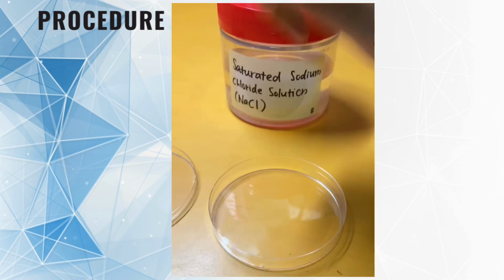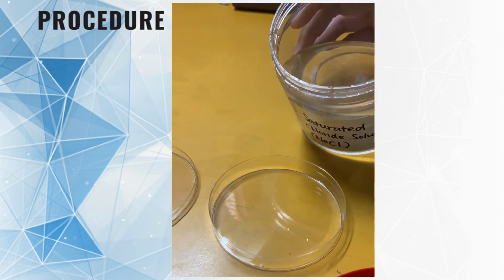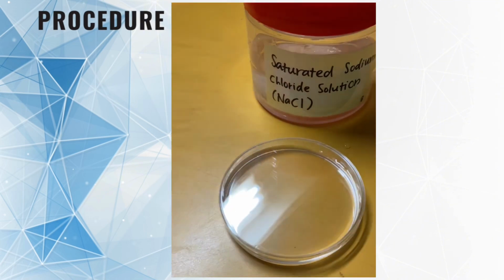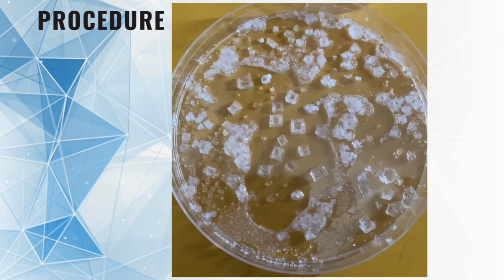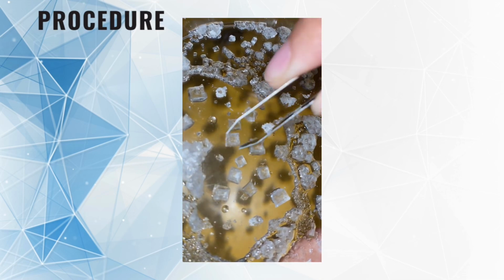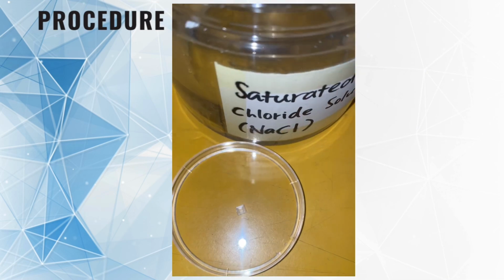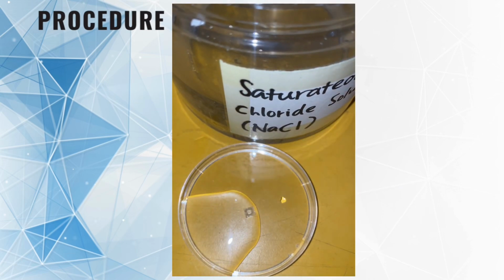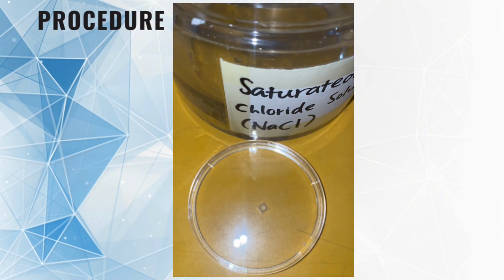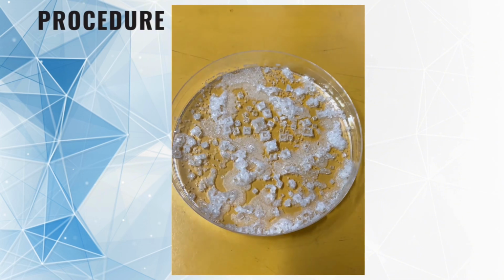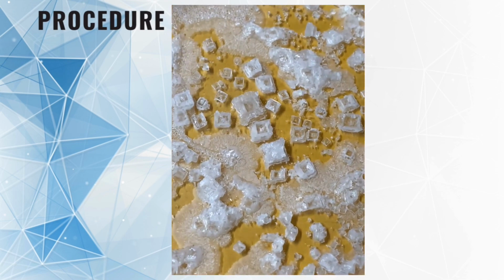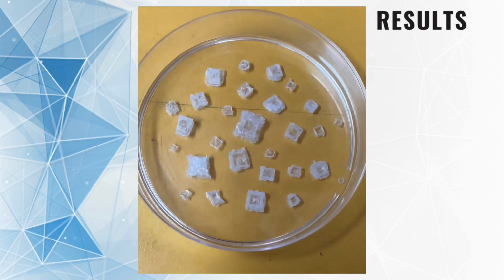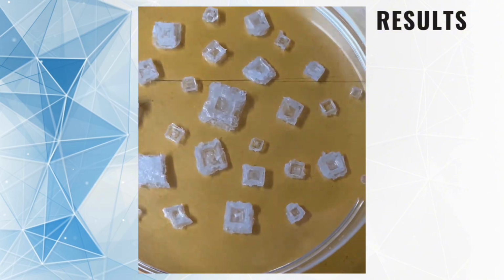a day. After a day, around 1 cm depth of the solution was poured into a petri dish and left undisturbed for 1 to 2 days. Once dried, a seed crystal was selected and transferred carefully to a smaller petri dish using a clamp, and a small amount of the solution was dropped using the dropper and left to grow undisturbed for several days, weeks, up to a month. Finally, once the crystal has grown, dry it on tissue paper. From this experiment, this is the result of my DIY face-centered cubic FCC crystal.